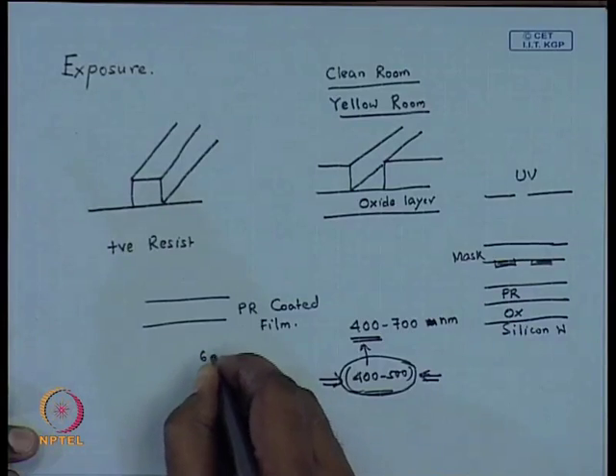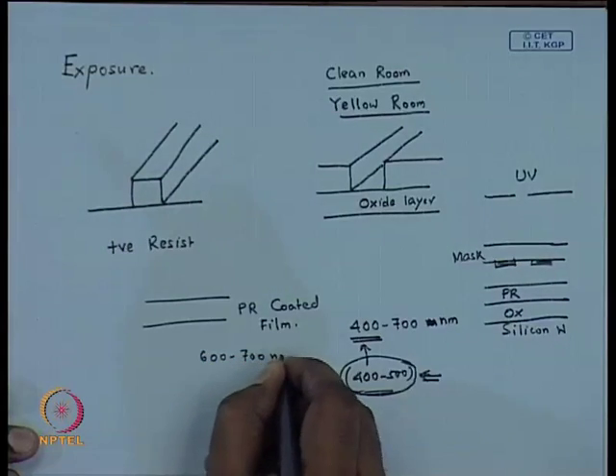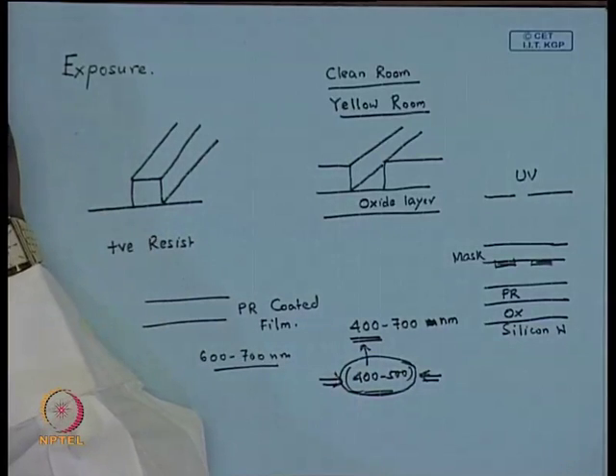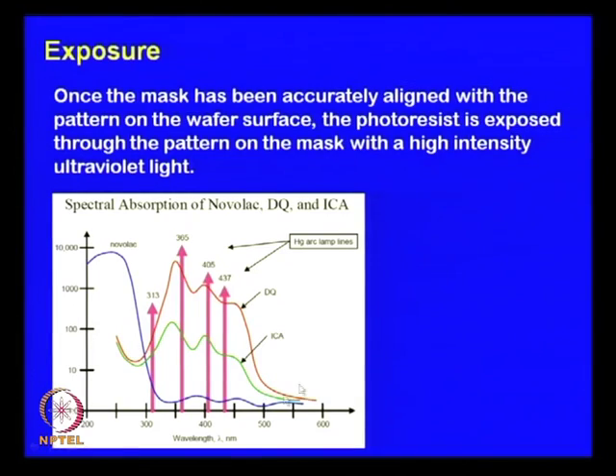So in a yellow room, typically all the doors, windows, curtains, everything is covered with yellow sheet, all the lights are yellow light. The intention is to keep the wavelength of the visible light in the range of say 600 to 700 nanometer. You see from this graph that beyond say 500, all these three commercially available photoresists, and I have taken the graph from Wikipedia, show very minimal absorption.